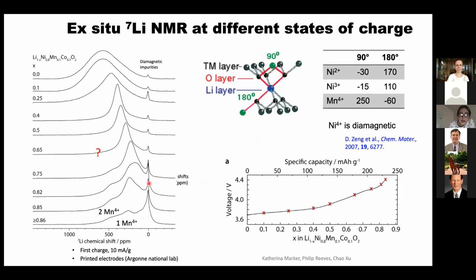This is now magic angle spinning, and I just wanted to show you what a magic angle spinning spectrum looks like. So you've got lithium in the initial compound here, and this lithium sees all of these paramagnetic ions, and the lithium and the nickels and the manganese are all arranged almost randomly in the structure. So you see this very broad spectrum. You start pulling lithium out of the structure and it sharpens up. And it's not intuitive why it should sharpen up, particularly when you get to the end, you actually get a broader spectrum again. And it's got these two distinct peaks here.